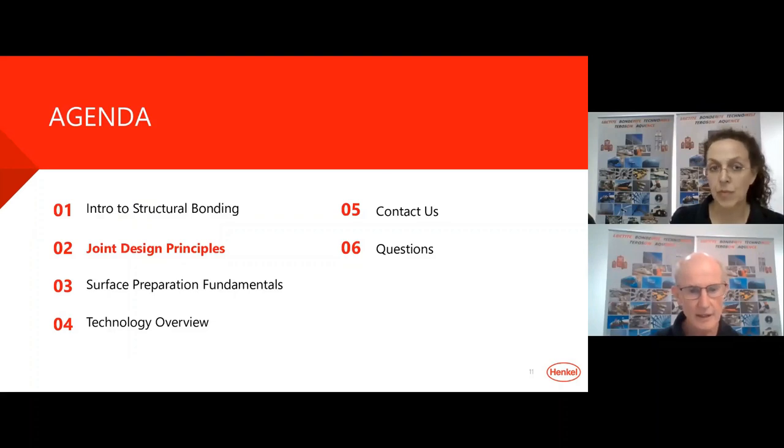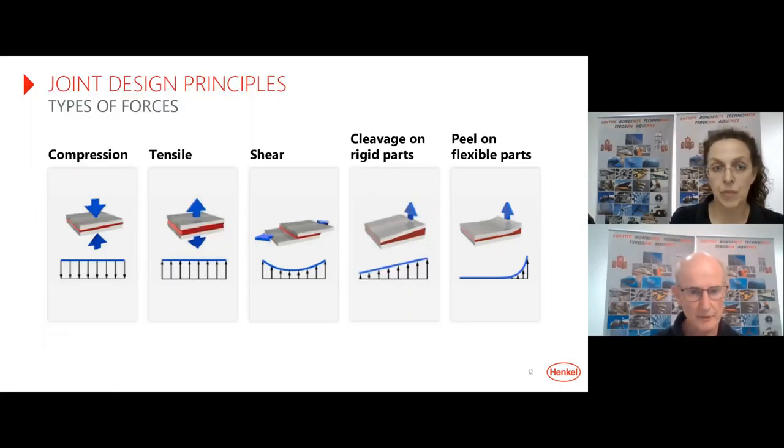So going on now to the design principles, if we go to the next slide. Now here on the left-hand side, the adhesive is shown to be in compression, and that's the ideal scenario for the adhesive. The second one along is in tension. The adhesive there has good stress distribution. And certainly if you can create the joint such that it's under compression or tension, then generally you get good results. A lap shear joint is also good. And in that case, there is a higher stress concentration at the end, but there are ways of overcoming that